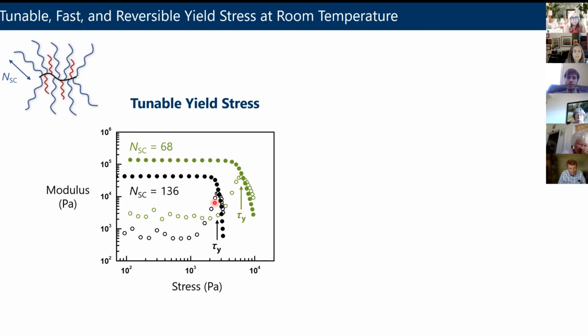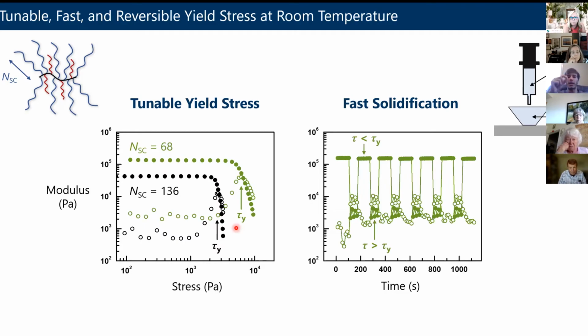You can see it's quite sharp. It just happens at some stress that we call a yield stress. Yielding means it goes from a solid that holds its shape to a liquid that does not. And that yield stress also depends on the side chain length. And if you oscillate back and forth between a lot of applied stress or pressure and a low amount of applied stress or not very much pressure, you can see at low applied pressures, the material is a solid because this G prime value is big, the G double prime value is small.